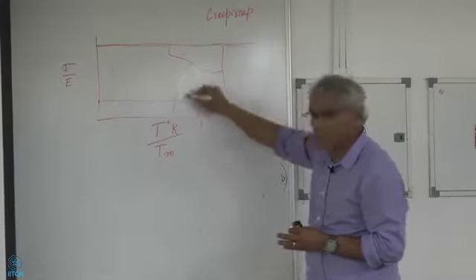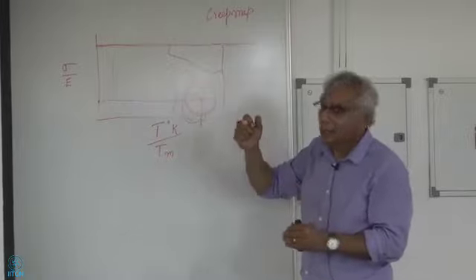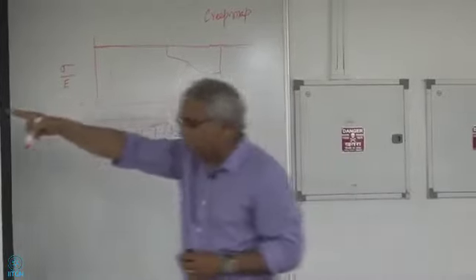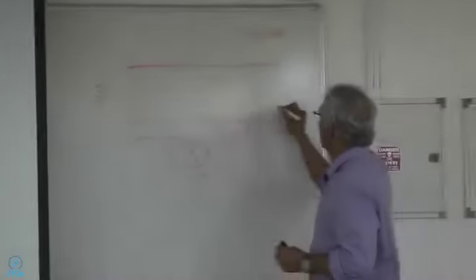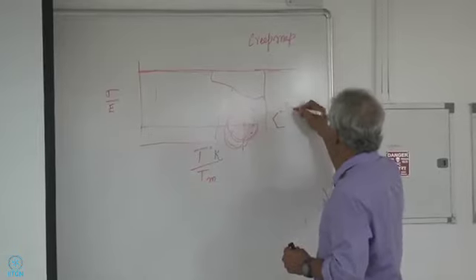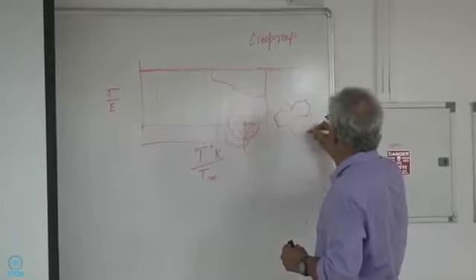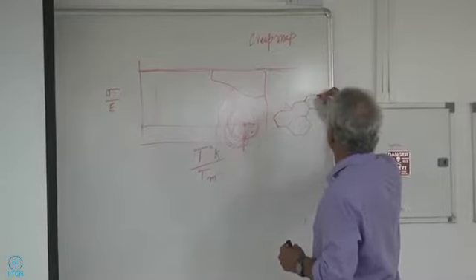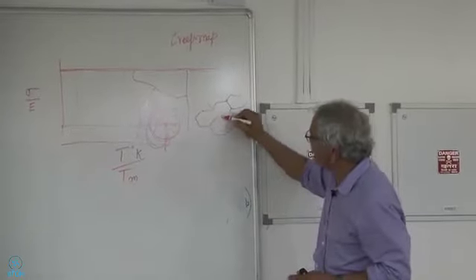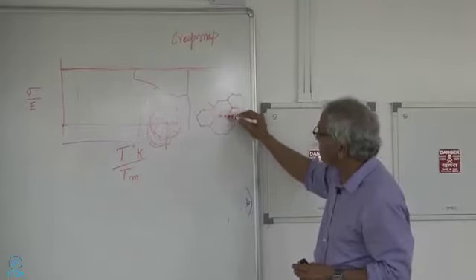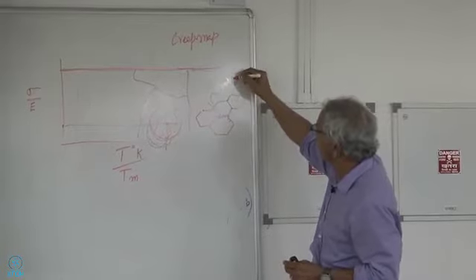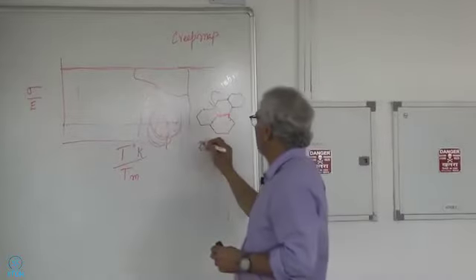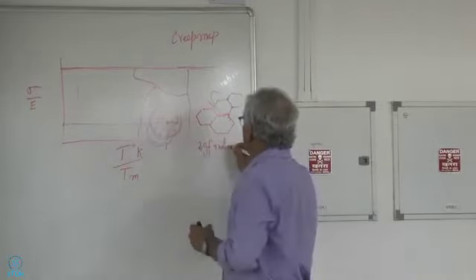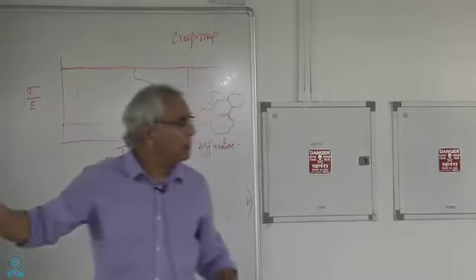So if I'm operating around this range, if I have a creep loading, that's the intergranular fracture I'm going to get, because all the diffusion is taking place along the grain boundaries. So all my vacancies are moving along this, which are going to form these voids, creep voids. So that's the intergranular fracture. We'll talk about more of this afterwards. I just wanted to put this in there. But remember this, we will talk about this afterwards, okay?